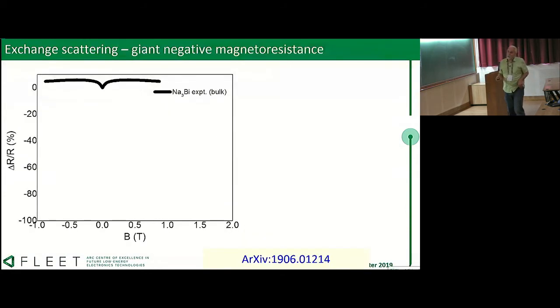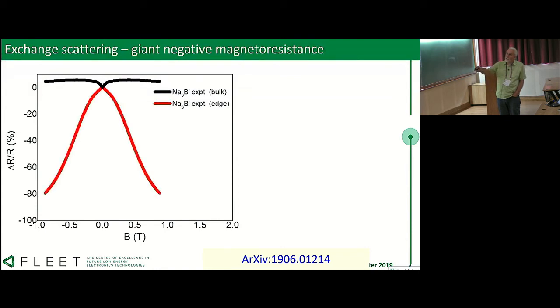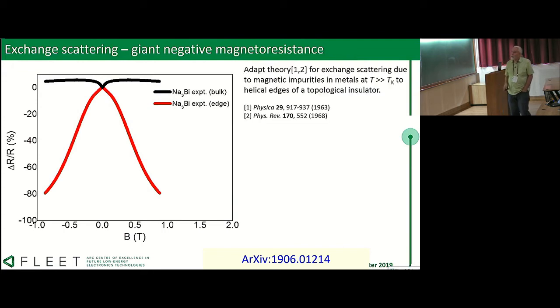Okay, and so there's an interesting effect due to that. One is that if we measure resistance as a function of magnetic field, this is this weak anti-localization that we see for the bulk. When it's in the edge conduction regime, you see that the magnetoresistance now is very large and negative. So we can compare to a theory for exchange scattering.